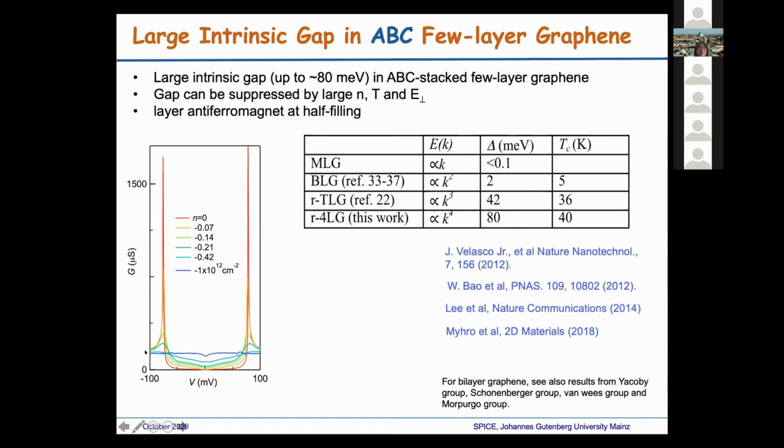We see this is differential conductance as a function of bias voltage. We see very large peaks in the dI/dV curves, which suggests a very large density of states piled up at the edge of the gap.